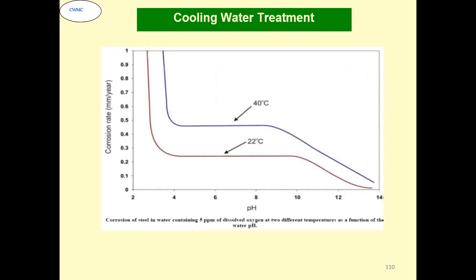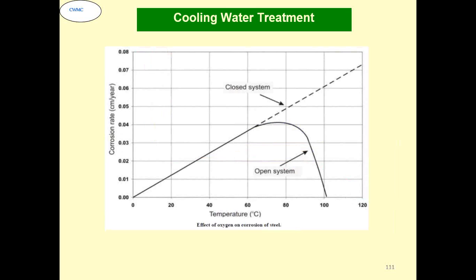Effect of oxygen also: the rates at 40 degree or 22 degree, as I said, almost double at every 10 degree. If dissolved oxygen is present, the corrosion continues, and if it is an open system, then it starts dropping, because the oxygen will form a corrosion product which reduces the effect of the corrosion.